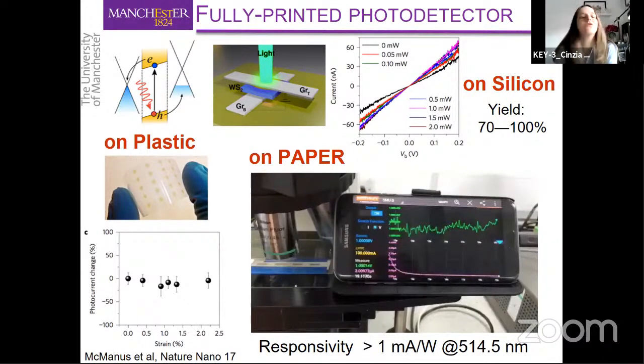So we printed 100 of those heterostructures with the same ink, with the same cartridge, all in one go. And we basically characterized all of them. And it turned out that none of these heterostructures is actually shorted. And this was a great result, because the thickness of the tungsten disulfide film is around 200 nanometers. And so if we would have intermixing at the interface, then the graphene from the top and the bottom would diffuse into the middle layer and cause a short of the device. But none of our devices was actually shorted.